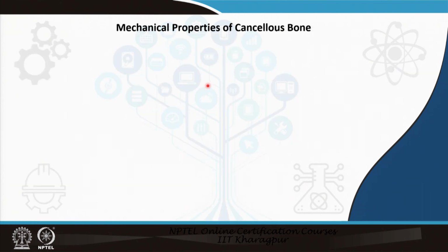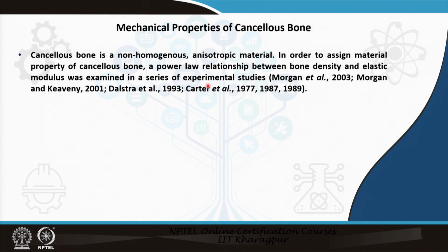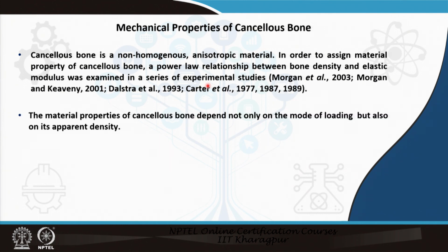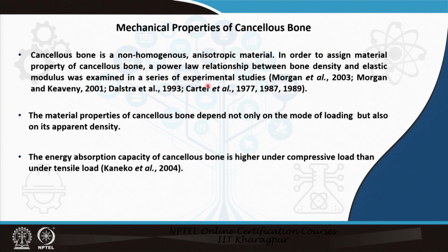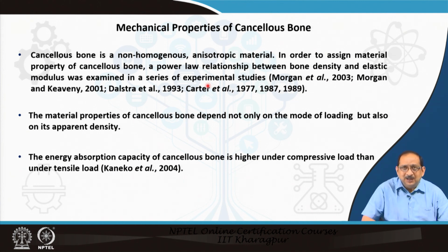Let me now summarize the mechanical properties of cancellous bone that have been presented in the lecture. Cancellous bone is a non-homogeneous or heterogeneous anisotropic material. In order to assign material properties of cancellous bone, a power law relationship between bone density and elastic modulus was examined in a series of experimental studies over more than 2-3 decades. The material properties of cancellous bone depend not only on the mode of loading, but also on its apparent density. The energy absorption capacity of cancellous bone is higher under compressive load than under tensile load.